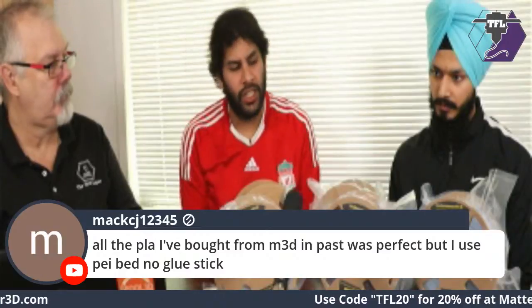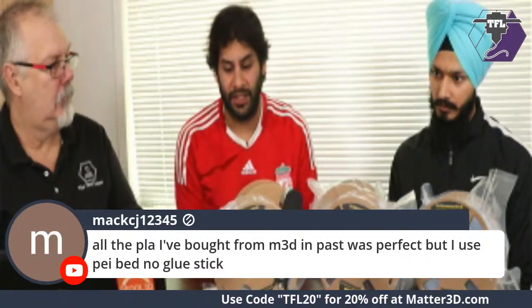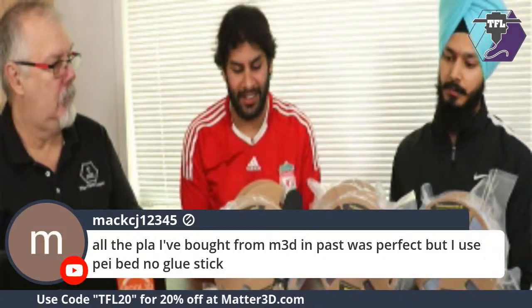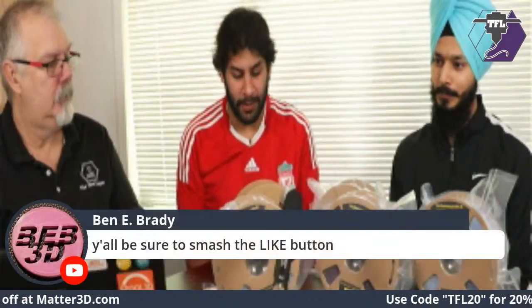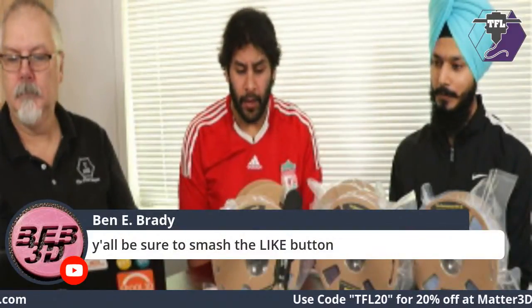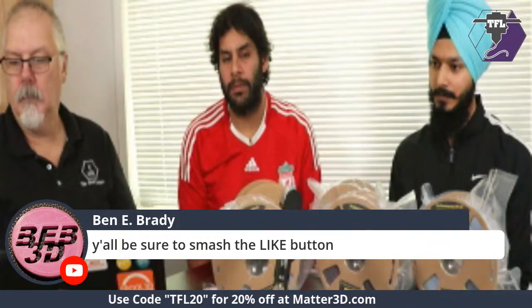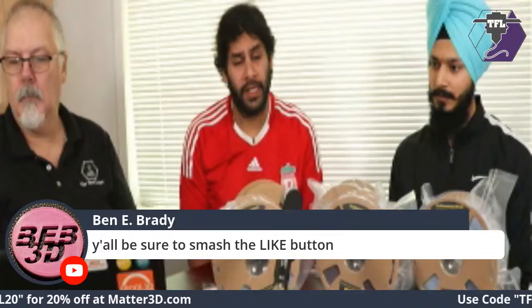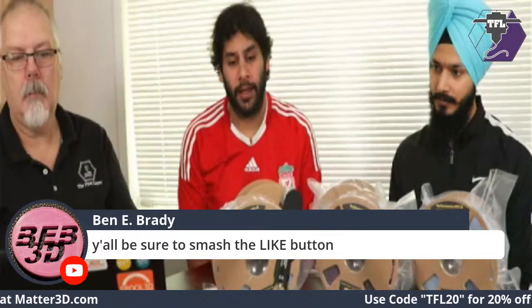So the glass transition temperature of our PLA, we actually did a DSC to figure this out. That's differential scanning calorimetry. It's quite an intensive experiment that we did at UVic. We figured it was between 60 and 65. So if you're just above the Tg, I print at 65, and it prints really well. But between 60 and 80, it should work really well for you.